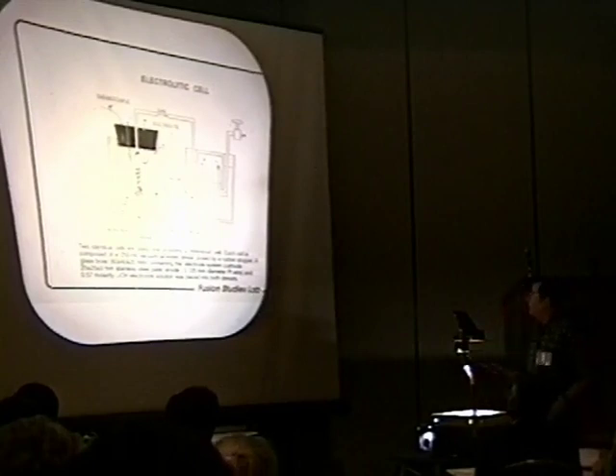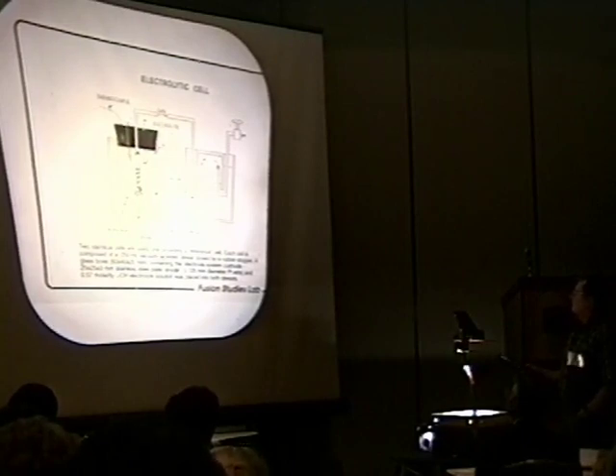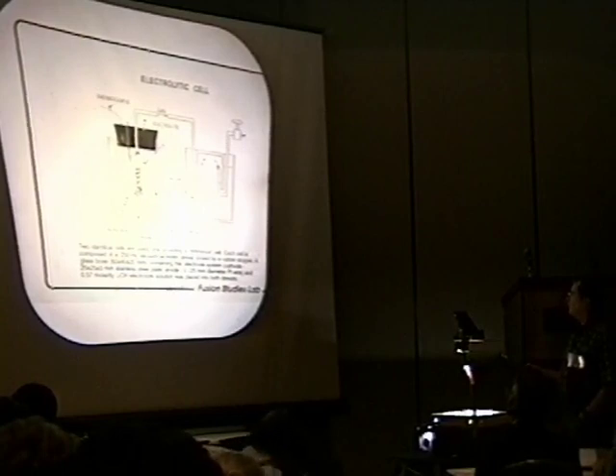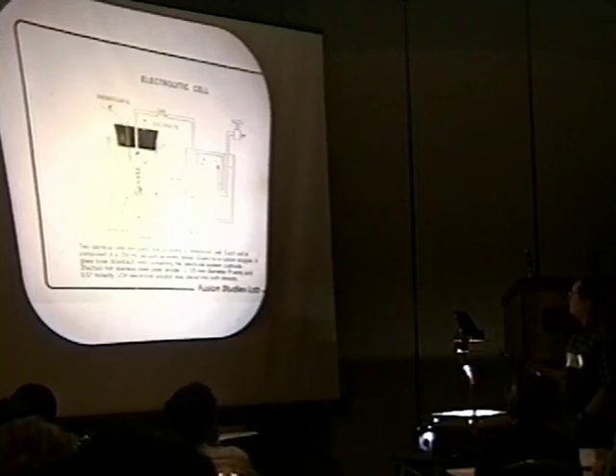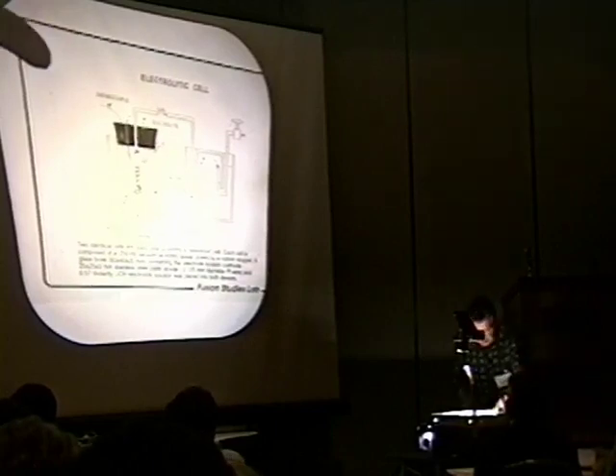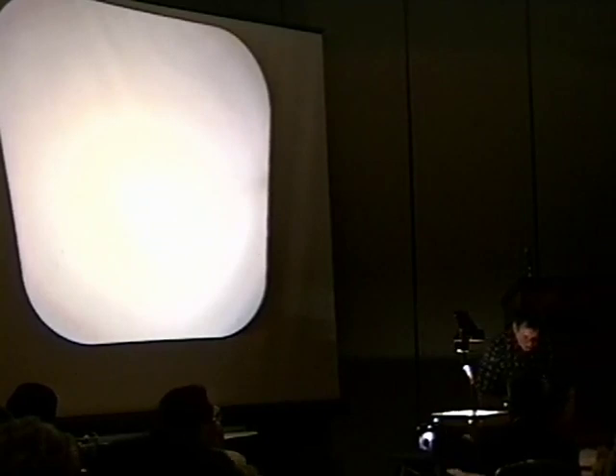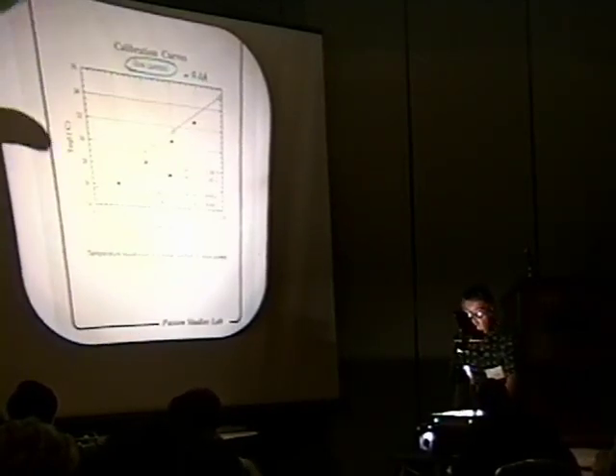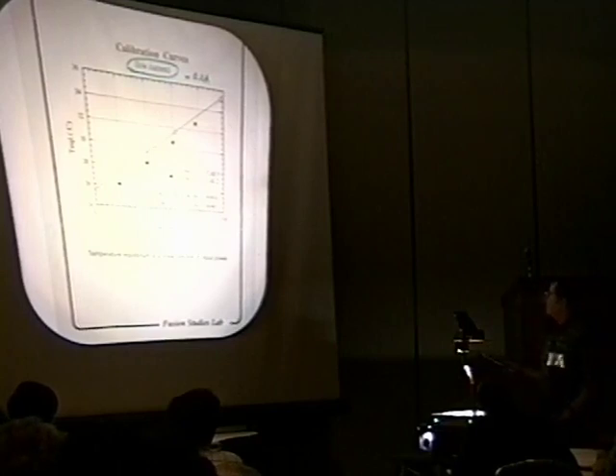So the actual electrolytic cell is an open type of cell. We have minimized volume around the electrodes, one electrode being a platinum wire, the second electrode being the thin film type. We've minimized the volume to get a maximum sensitivity. We have a gas collection box here so we can observe any possible differences in gas evolution which might cause difficulties. For calibrations, today I showed two regimes, one a low temperature or low current regime, the other the high current, and the calibration for these paired cells are shown here.